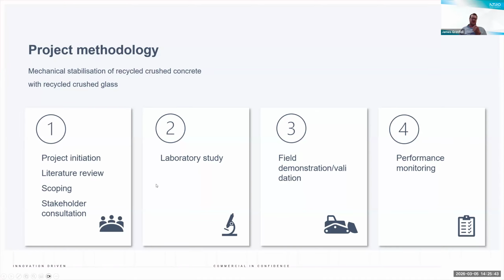So again, this time, this was actually working with another local government entity within Australia. In this case, they had a problem recycled crushed concrete material, so a recycled material. They also, within that council at the time, had a problem with waste glass. And therefore, we were trying to look at whether or not we could optimize the performance of the recycled crushed concrete through blending with recycled crushed glass.